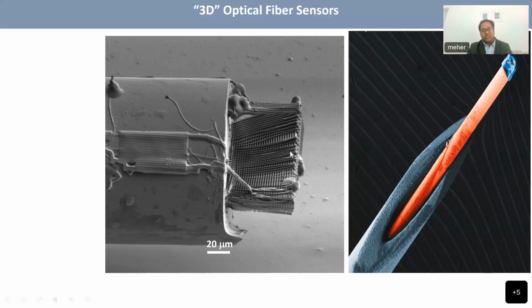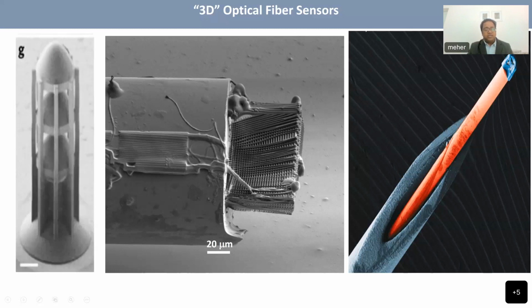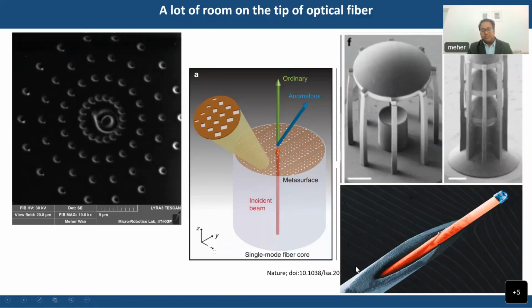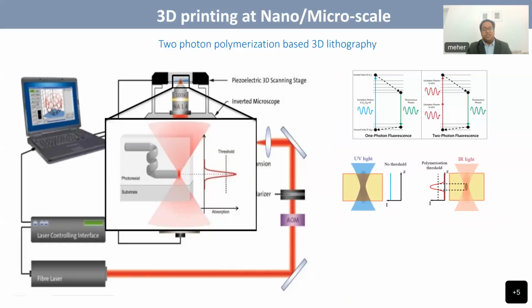We also tried this; this picture is actually from our lab. I personally tried this, and this is the woodpile structure I wanted to deposit on the tip of the fiber. Here you can see that we could locate the center of the fiber and deposit something controllably on the tip. But this is not too good, so some optimization was needed, and it's in process. This is the reference, a paper published in Nature by some other groups. We wanted to follow this up for sensors, and the technology used to deposit these nanostructures and microstructures on the tip of the fiber is two-photon polymerization based 3D lithography.